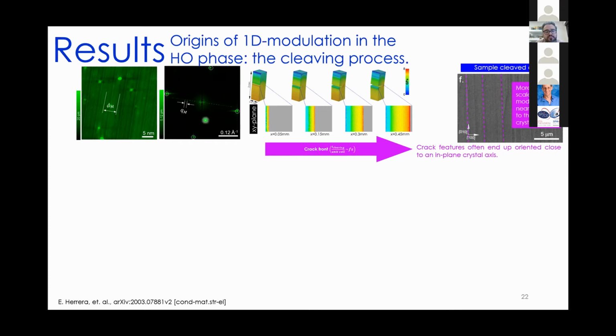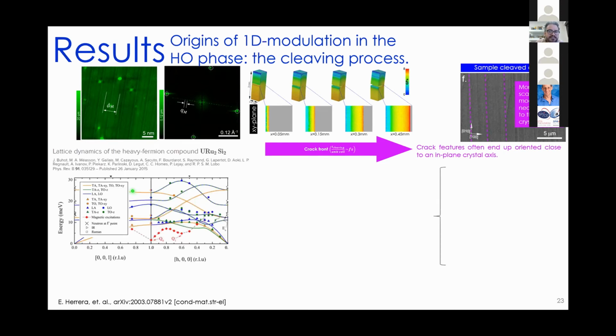So how can we explain this? What is the physics behind it? It is important to notice that studies of the lattice dynamics in uranium ruthenium silicon-2 show that the energy scales of the phonon modes, optical, longitudinal and acoustic modes, are all of a similar order of magnitude. The magnetic and electronic excitations, represented here by Q0 and Q1, are also of the same order of magnitude as the others, which means that interactions between them are created. If we are in this range of energies, it will be very easy.